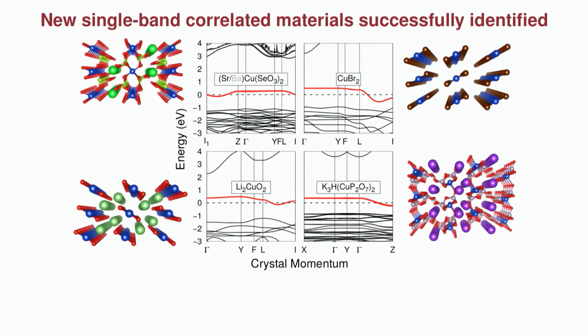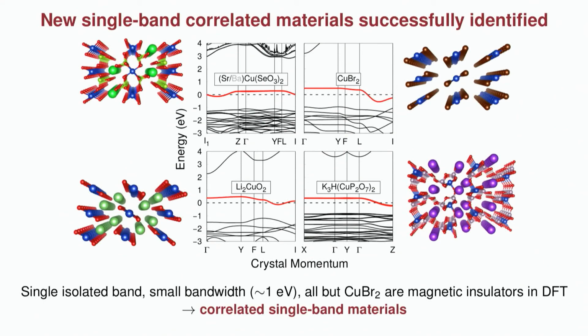In addition, I'll note that in addition to achieving this one band characteristic, we have evidence for these materials that they also will exhibit strong electronic correlations. So first of all, the single isolated band has a small electronic bandwidth, in all cases no more than 1 electron volt. So what that tells us is that effectively the U over T ratio is very substantial.